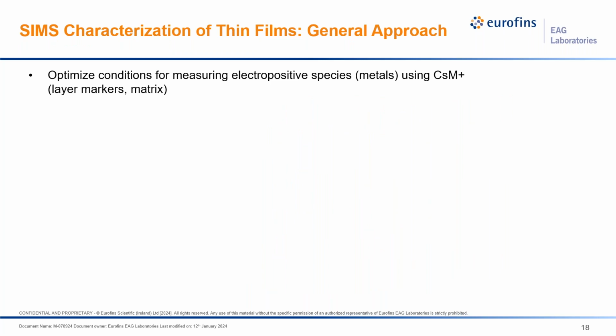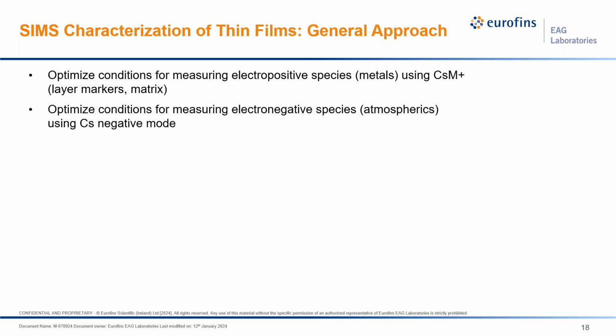Our general approach for thin films: often these thin films have a request to measure a mix of electropositives, for example metals, as well. So we will optimize conditions for measuring these in the MCs+ mode. We can then optimize conditions for measuring electronegative species, in particular atmospherics, again carbon, hydrogen, nitrogen, well, not nitrogen particularly, but carbon, oxygen, and hydrogen, using cesium negative mode.